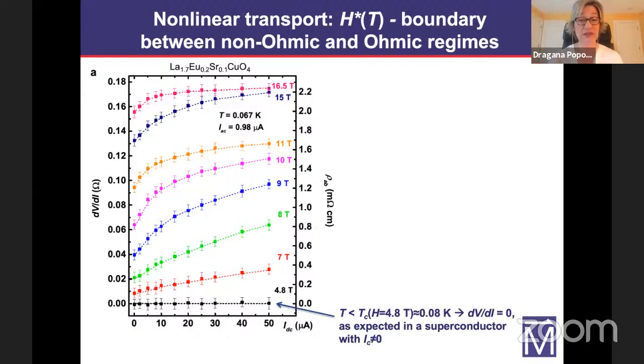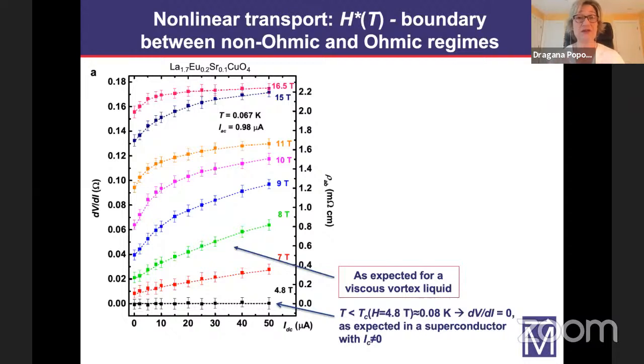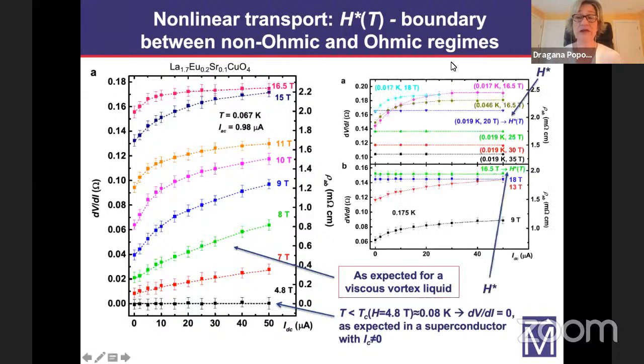And then we keep increasing the field. TC is suppressed to zero, but what we find over a wide range of fields is that even though resistance in the limit of zero excitation is finite, the resistance depends on the current applied. And this is exactly what is expected for a vortex liquid, that is, for vortices that are moving in the presence of disorder. We can keep increasing the field further, and eventually at some point you get to the field where transport becomes ohmic. It doesn't depend on the applied current, so you can in this way determine this field that we label H star, which represents the boundary between this non-ohmic and ohmic transport.